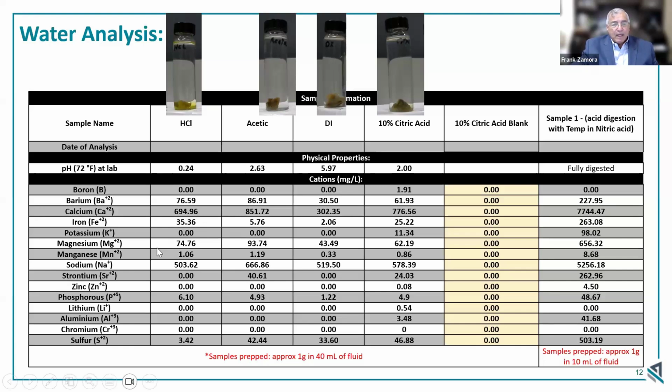The potassium, and we're talking about the divalents here, the magnesium, manganese, not much manganese, sodium content, strontium. The one thing that I found interesting out of all of this is that the one element that actually came out pretty consistently over time is this aluminum. And aluminum, as we know, a good partial transitional metal, is a very good crosslinker as well. So is this also a contributor to causing the firmness of the gummy bear or not?